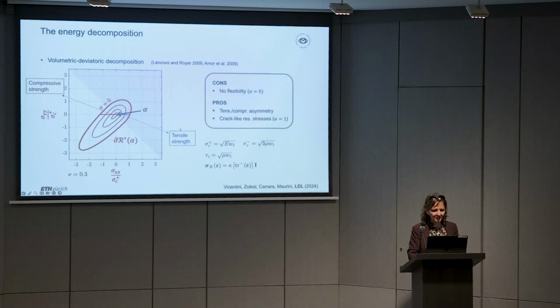So this is really not satisfactory. And this is the reason why in the plate with hole under compression, this decomposition gave us the wrong nucleation. So it nucleated under compression in the wrong point, and this led to all the issues.